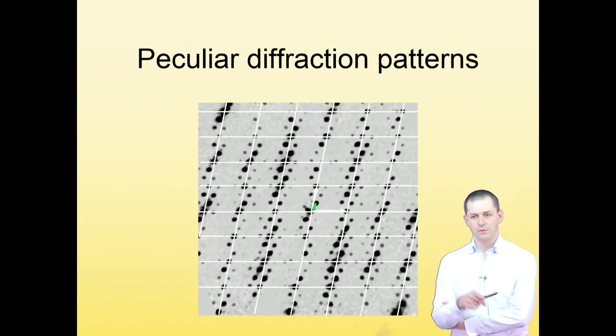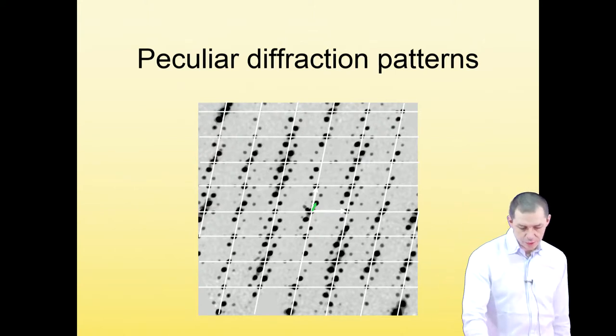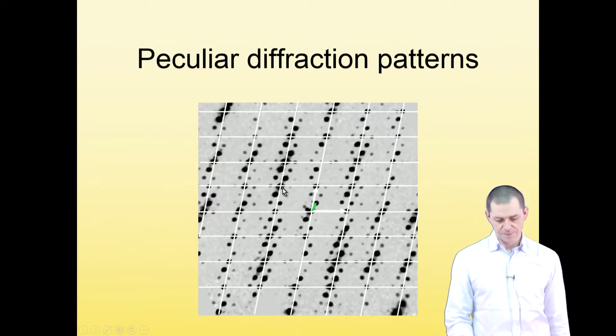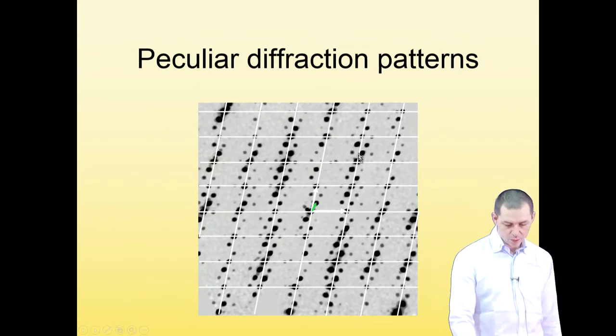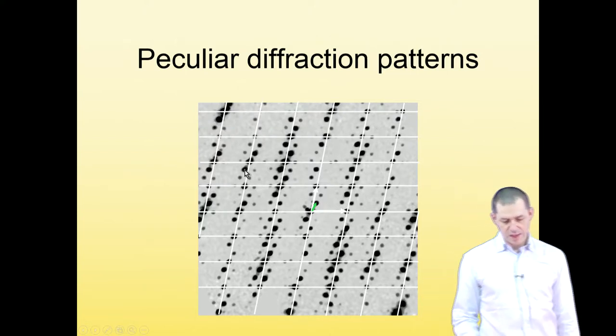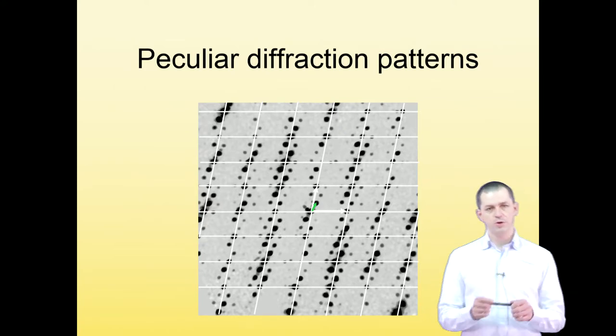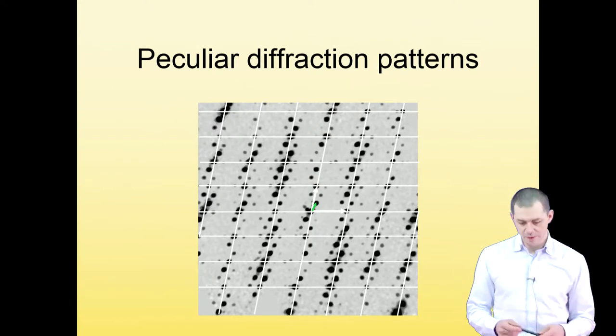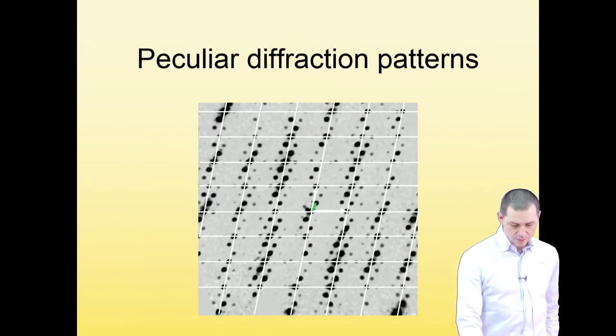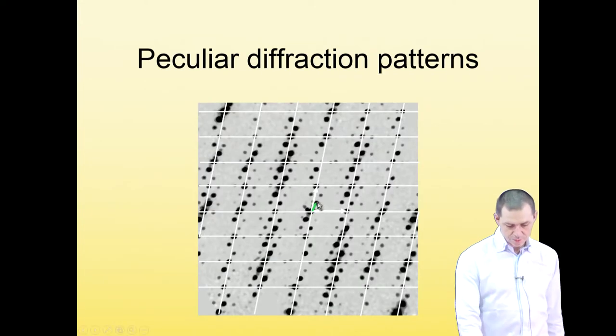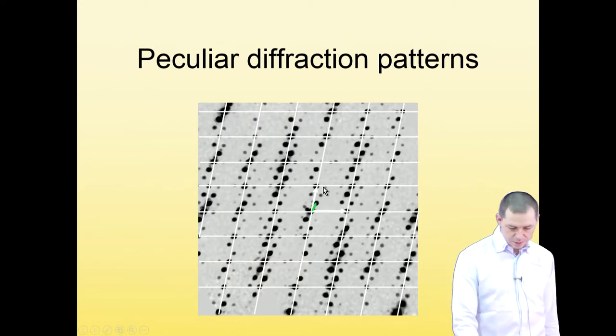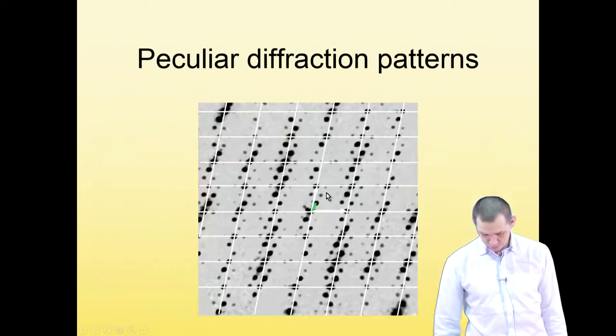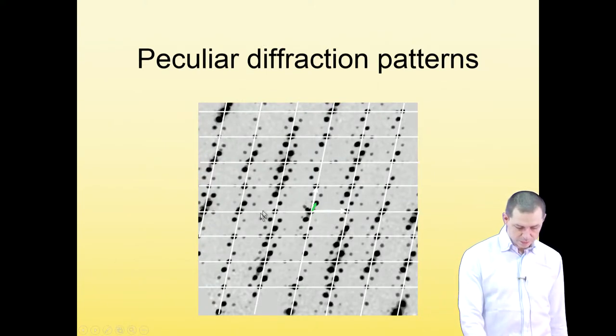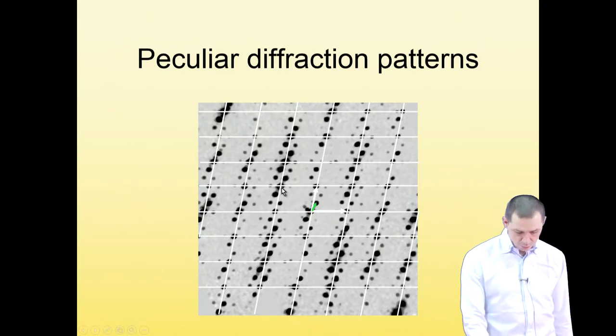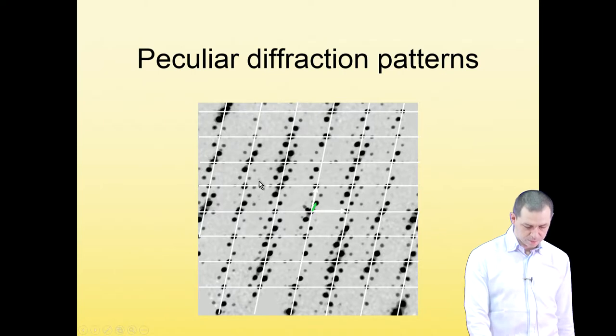However, what is possible is to find a very simple lattice and associate each row of these reflections to one node of the lattice. You see these long rows of spots, they are all centered on nodes of the lattice. And then to describe the complete pattern, you need to introduce an additional vector, which we call the modulation vector or q vector, which points from the nodes of the lattice to the peaks away from the lattice. So, for example, this peak is obtained as a node of the lattice plus 1 times the modulation vector. This is 2 times, and this is 3 times. If you look in the pattern, you find cases where you need to go even 4 times. So this is 0, 1, 2, 3, 4.